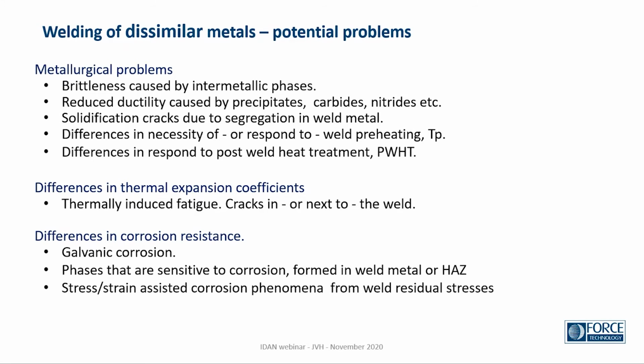We could have differences in corrosion resistance. Two metals with different corrosion resistance in the same environment. There might be one which is noble, causing the other one to corrode faster than it would by itself. In the structure itself, in the weld, we might get phases that are sensitive to corrosion formed during the solidification. And also we have residual stresses around a weld, and some corrosion phenomena are related to these stresses. And of course, if we have items which have not been welded, then we don't have the stresses, and there's less risk or less form of corrosion.